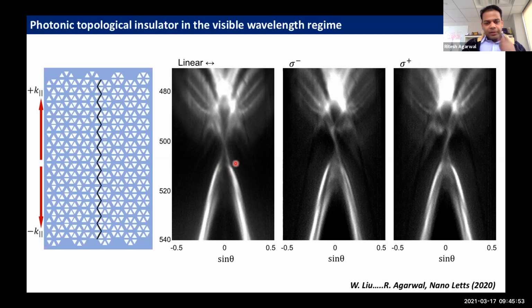So linearly polarized light excites both right and left circularly polarized photons. One propagates in one direction, you can see it has a positive slope. The other has a negative slope, so it propagates in the other direction. But if you shine only right circularly polarized or left circularly polarized light, you can see only one of the two modes is selectively excited.